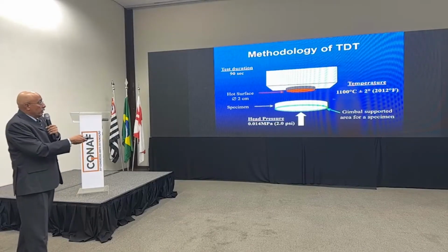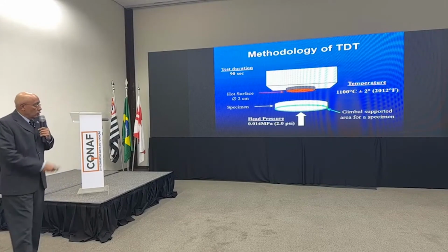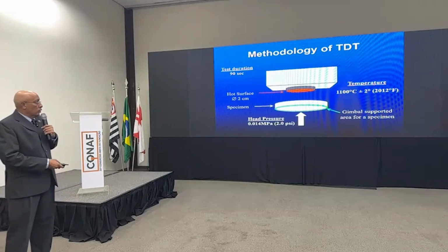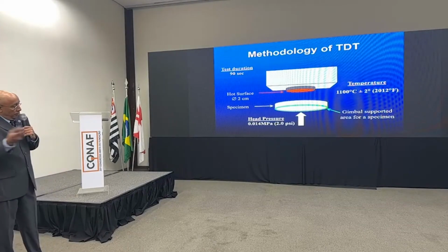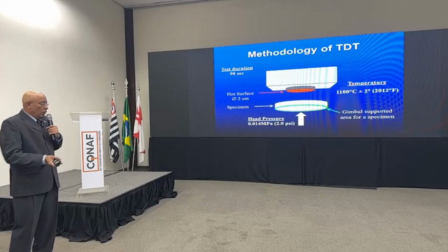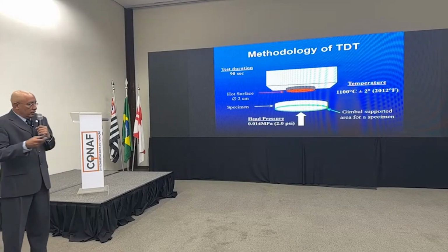In this case, we were looking at a copper-based alloy, so the test conditions were closer to 1000 degrees C, or if it was an aluminum alloy, we would look at head pressure against an aluminum temperature like 700 to 760 degrees C. And this is how our mechanics or thermomechanics would relate.